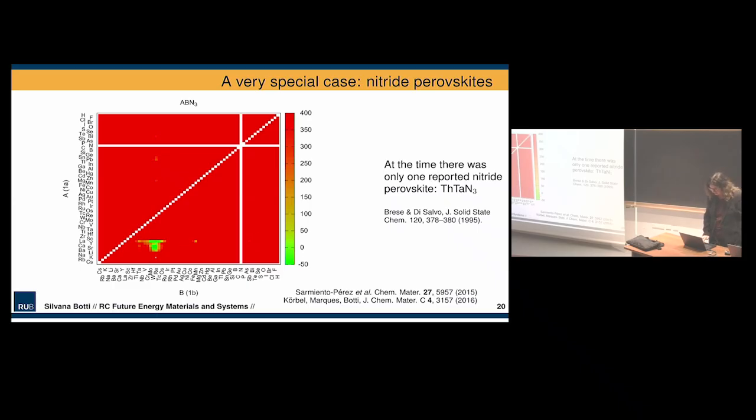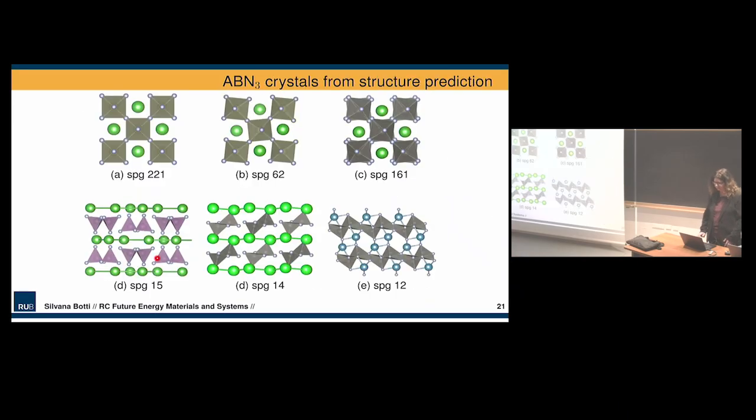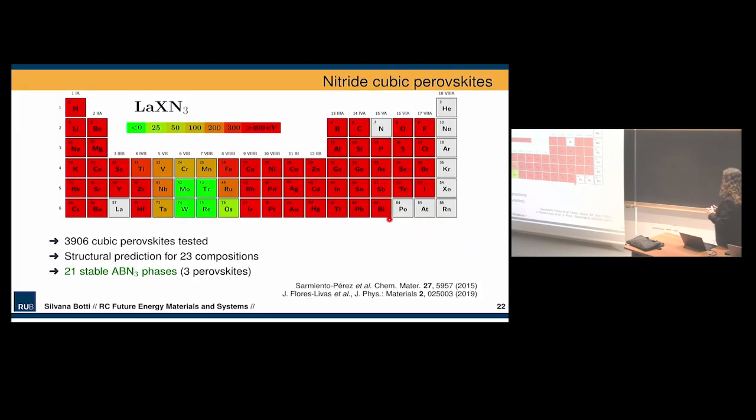And here there is this cluster. If you look in more detail, we then did the structure prediction. We allowed larger supercells, and we saw that some of these green things were not remaining in the crystal structure of perovskite. Some were getting just distorted perovskites, but some were breaking the octahedra and getting to some monoclinic crystal structures. Those are still compounds that we have to add to the hull, but they will very likely not be perovskites, because there are some phases that are lower in energy that destroy the octahedra.